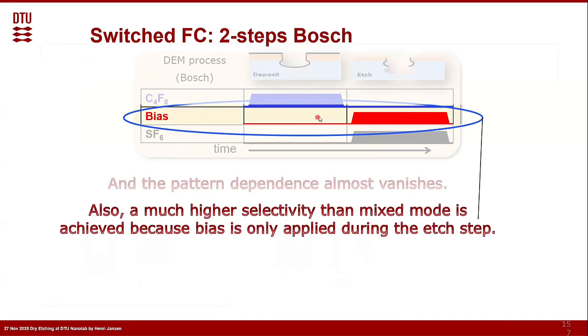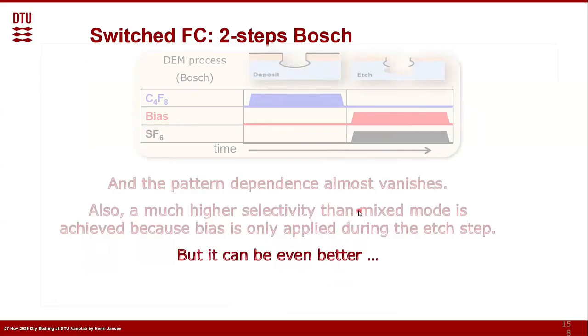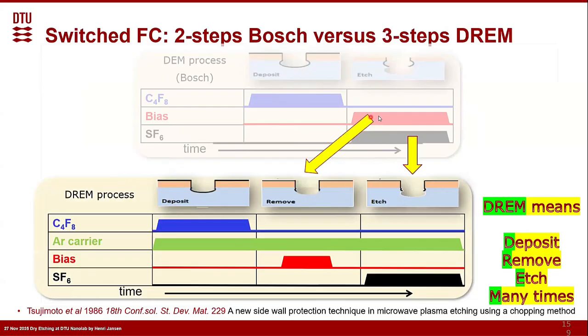And also because we are not using the bias all the time, but only part of it, the selectivity can be much higher than the mixed mode. But we can do it even better. We can even split it, because just beforehand I said, when you have deposited the fluorocarbon, initially the etch process will not do anything because it still has to remove the bottom. So we can do that in a separate step.